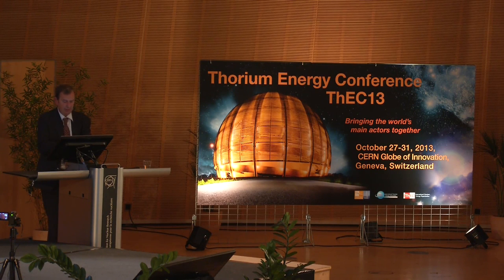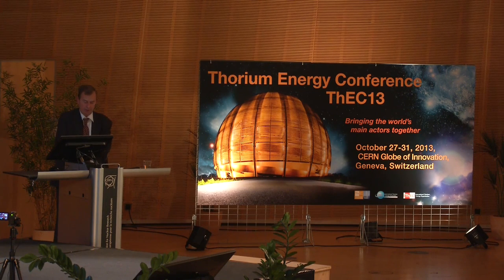I will come back to that. If one considers the thermal behavior and the stability of thorium MOX compared to uranium MOX, thermal diffusivity measurements on unirradiated thorium MOX have been performed at the Joint Research Center of the European Commission, ITU, and it's better than uranium MOX. Let's come back a little bit.